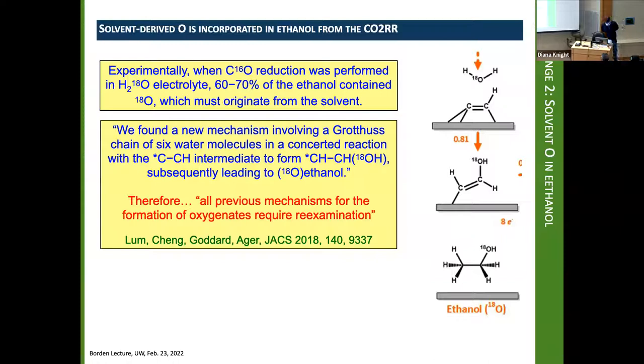We found a new mechanism involving a Grotthuss chain of six water molecules in a concerted reaction with the *CCH intermediate, which I didn't mention before, to form *CHCH18OH, subsequently leading to oxygen-18 containing ethanol. And in particular, and amusingly, therefore, all previous mechanisms for the formation of oxygenates require re-examination, in particular the one I told you about. All right.